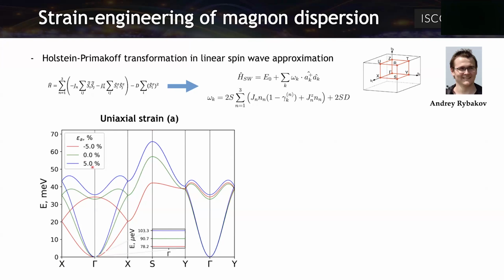So when we are increasing, we are affecting mostly this gamma-X direction in reciprocal space, that is parallel to the A-axis in real space. And we are increasing the dispersion here. So this is making these waves travel faster. And we are also affecting the magnon gap, that is coming more as an effect of the anisotropy, but we can observe here that this is also increasing. This is the blue line, expanding our material at 5%.